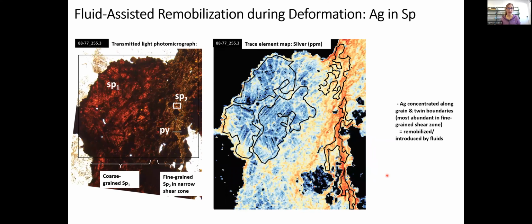Now, in contrast, here we have a map for silver, and it behaves a lot like lead that we saw earlier with the pyrite, in that it's concentrated along grain boundaries. You can see that really clearly in these coarse-grained areas where it's sitting on grain boundaries, but also sitting on twin boundaries, these parallel lines over here. So this silver is really kind of going in along any boundary it can find. We have very high silver in this area.